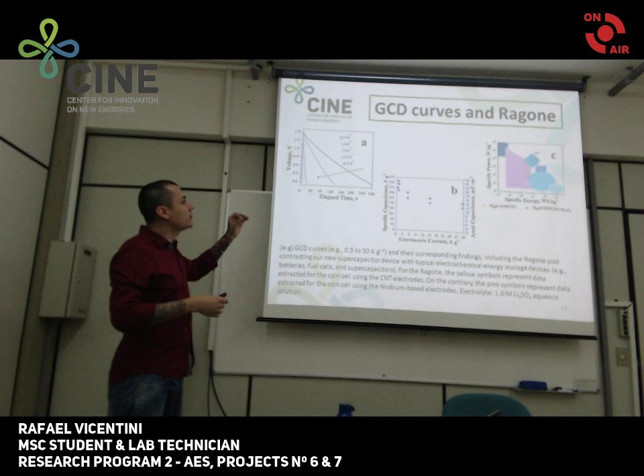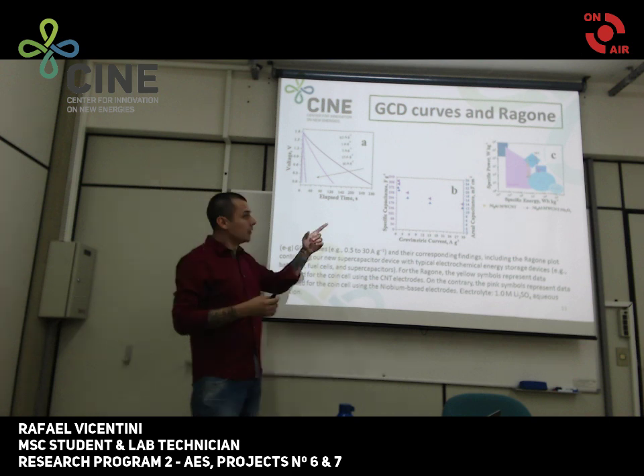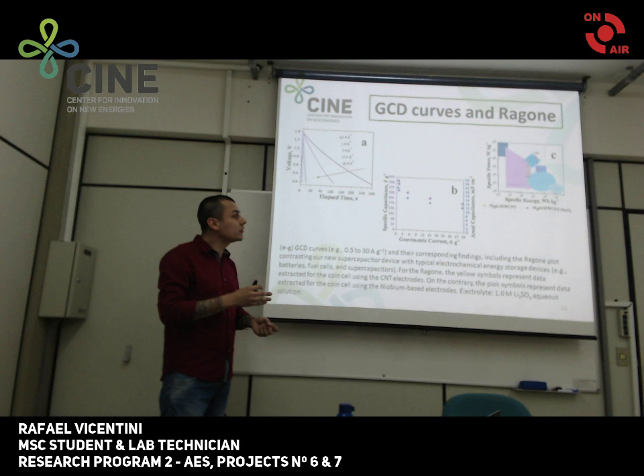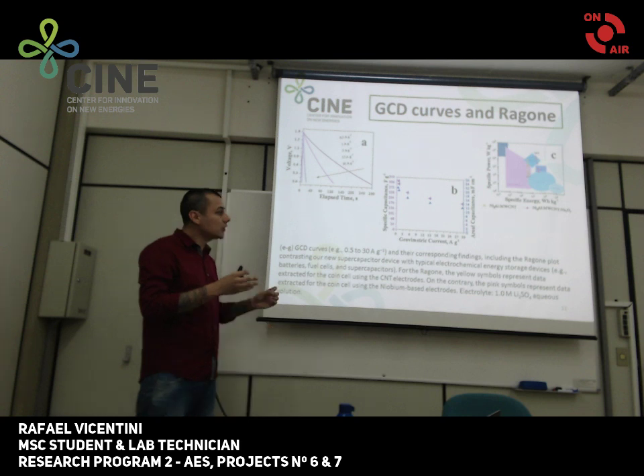Here, the Ragone plot is contrasting our supercapacitor with other typical electrochemical energy storage devices, like batteries, fuel cells, lithium-ion batteries and capacitors, and so on. Then, after all these results, we can conclude that the developed material composed by carbon nanotube and niobium pentoxide has excellent electrochemical properties. Then, in conclusion, we report here a very interesting carbon-based material to be used in a supercapacitor.